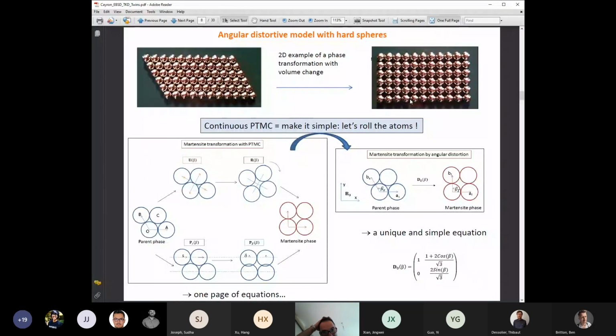Actually, I came back to my initial problem. I wanted to explain this continuous rotation, and I also wanted to get a better idea of how the atoms move during a phase transformation. So I made it as simple as I could. I said, okay, let's consider in a metal that the atoms are hard spheres, more or less. In magnesium, for example, the c over a ratio is 1.62, that is close to the ideal one you could expect by stacking hard spheres.